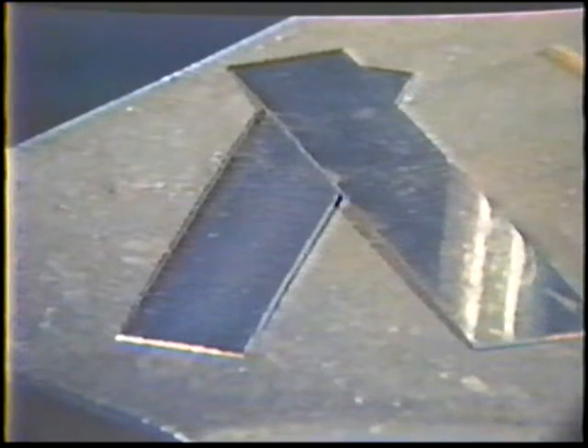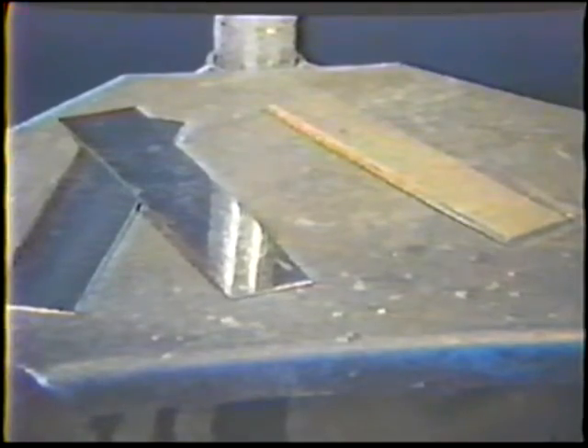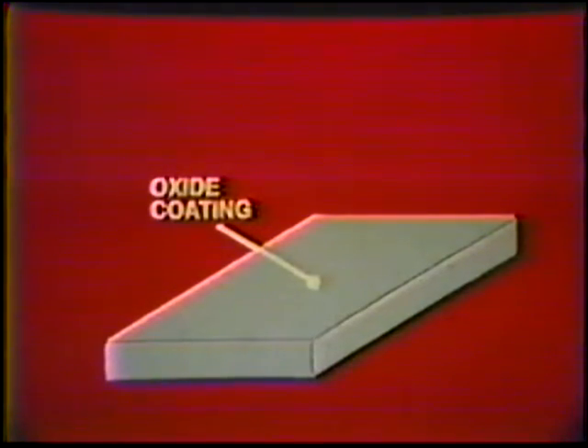They are called stainless because they resist rust. Generally, they retain their original finish under corrosive conditions, as compared to ordinary steel and iron which rust or corrode. When exposed to oxygen in the air, the chromium tends to form an oxide on the surface of the steel. This oxide coating protects the steel from further oxidation.